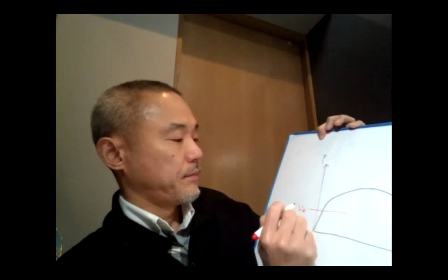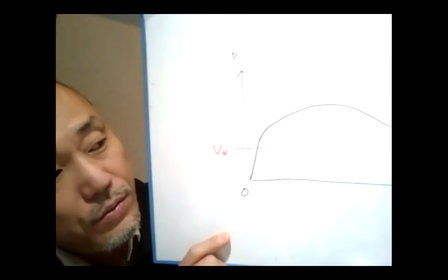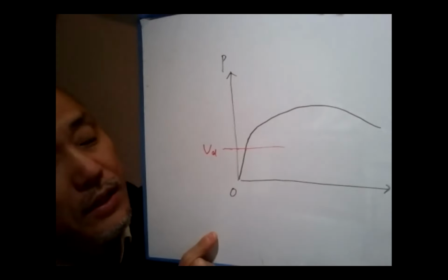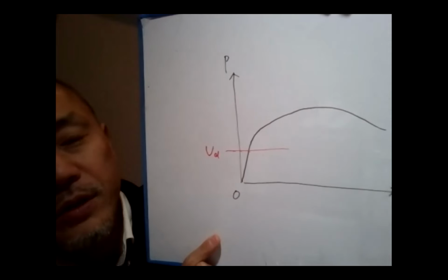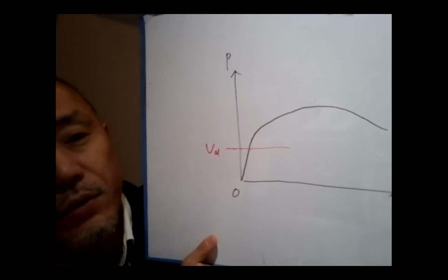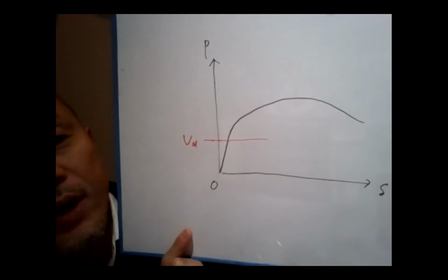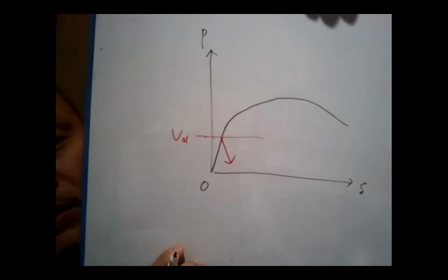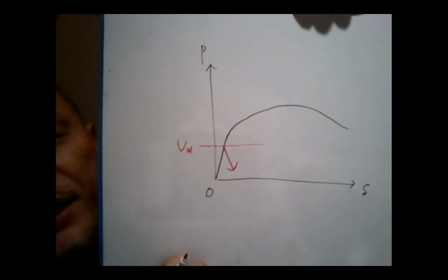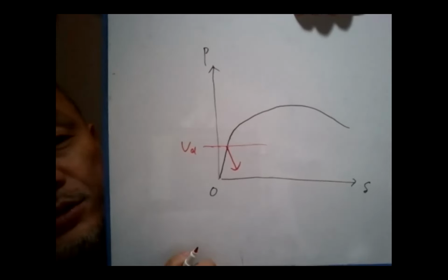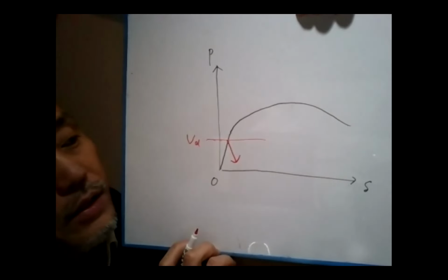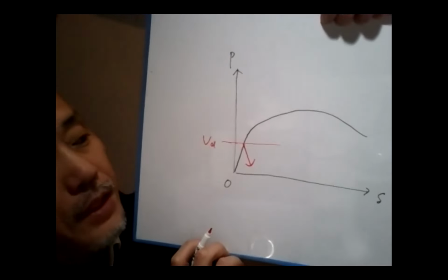VD, what will happen when the shear capacity in this graph, VD? D means design. So if the shear capacity calculated by design code, VD, is at this level, what will happen? Then, without showing a ductile behavior, black one is the ideal full performance. But due to a lack of shear capacity, reinforced concrete column will fail in shear. So that's why shear capacity should be increased.